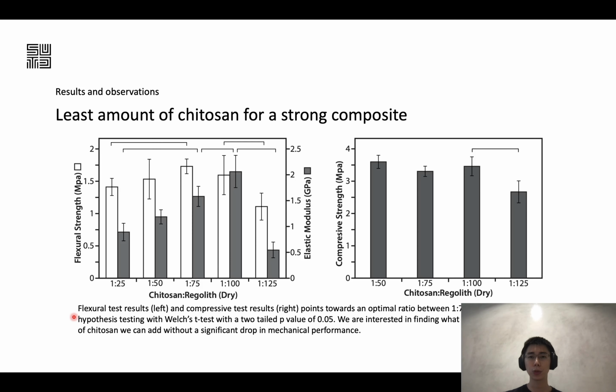Now, as we made the composite in varying ratios and subjected them to mechanical tests, both flexural and compressive tests, what we find is that there is actually an optimal point or optimal range. Now, in these two graphs that you see over here, the horizontal bars between the groups, correlating two different groups, actually signify significant differences.